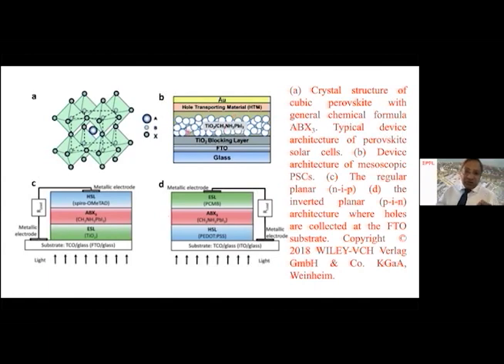Now, if we remove this mesoporous TiO2 layer, then it's called a planar NIP configuration. It's exactly the same as B, except we have removed the TiO2 nanoparticles, using only a compact layer of TiO2, followed by the absorption layer, that's the perovskite, followed by the hole transporting material.